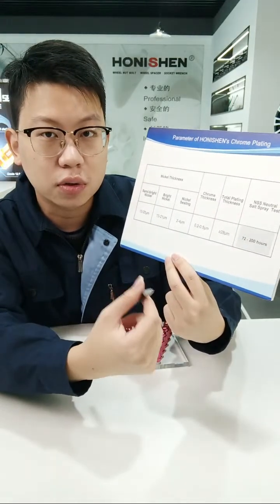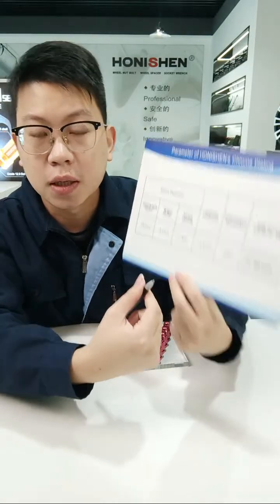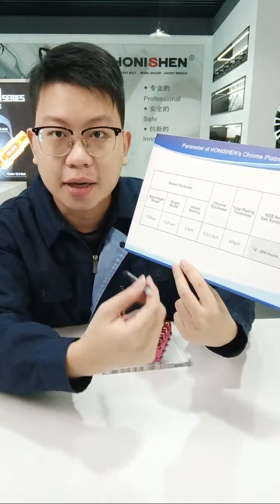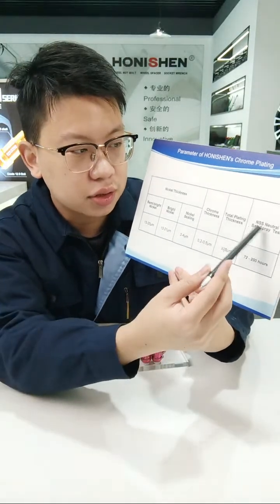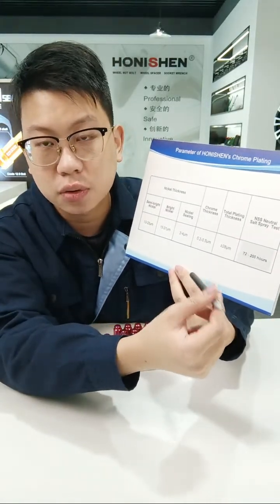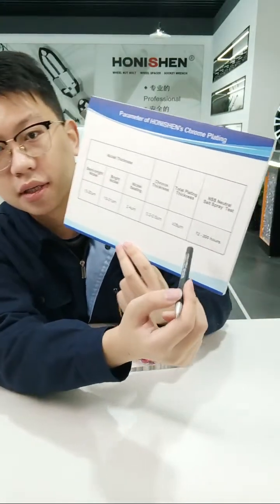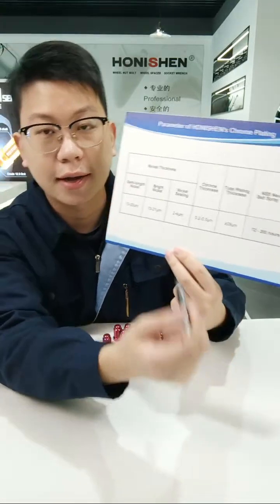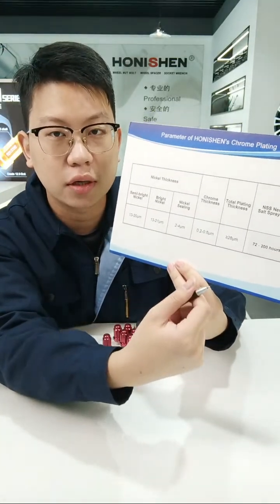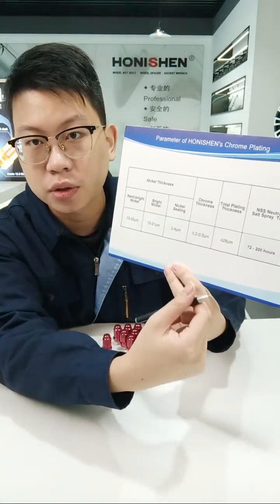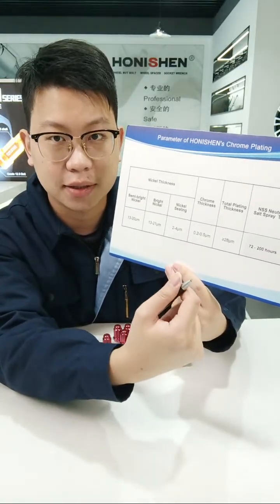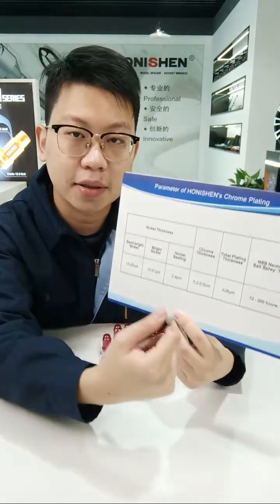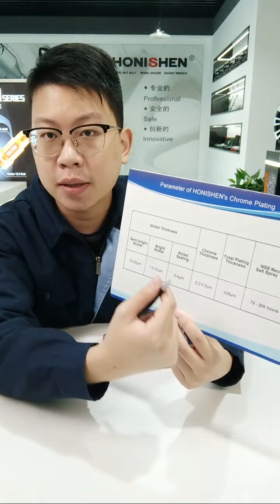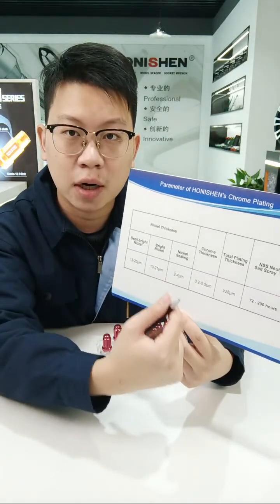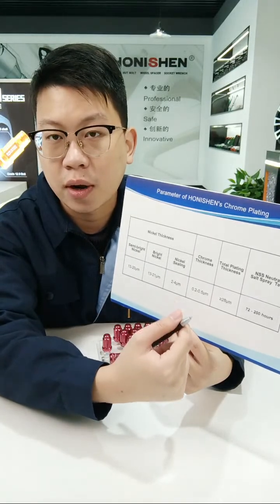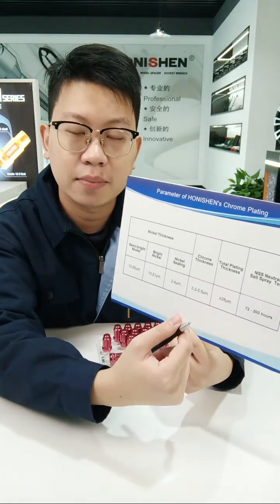So if you want good quality wheel lug nuts, you should make the layer thicker. And just like I told you about the NSS test, the neutral salt spray test, it should be more than 72 hours. We usually can pass 72 hours to 200 hours. And if you want the black chrome one, we can even pass the 500 hours neutral salt spray test. And that's all for my today's introduction for the electroplating quality and potential difference. Maybe the content will be a little boring, but this will be very helpful for the purchase when you purchase the wheel lug nuts from our factory or many other manufacturers.